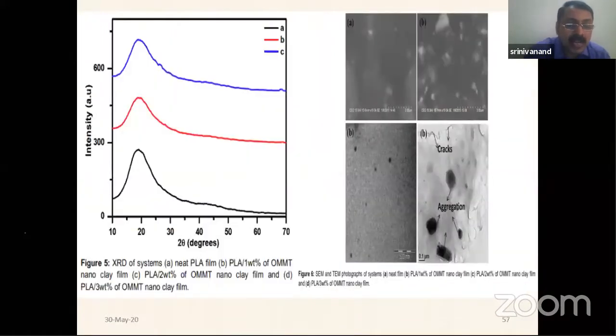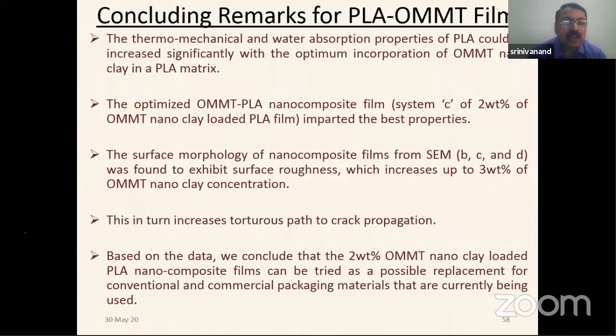We did the XRD study as well, and we can see the polymer forms an intercalated nanocomposite. Intercalation is a process where the polymer chains get infiltrated into the clay galleries. The 2 theta value is reduced as we keep increasing the percentage of montmorillonite clay. This is the concluding remark from our study: we optimized the percentage of OMMT in PLA at 2%.